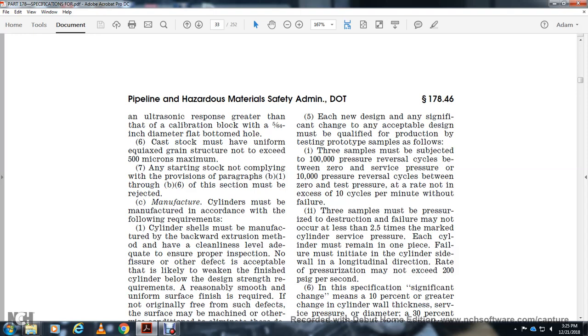These 3 samples must be pressurized to destruction. The failure pressure must not be less than 2.5 times the marked cylinder service pressure. Each cylinder must remain in one piece. The failure must initiate in the cylinder side wall in the longitudinal direction, with a rate of pressurization not exceeding 200 psi gauge per second.